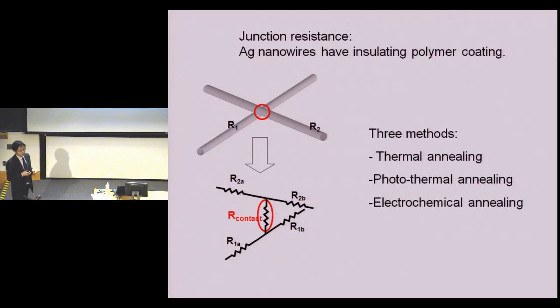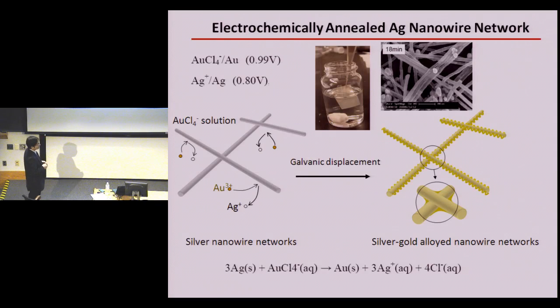So in our group, we found different ways to fuse the two junctions together to decrease the sheet resistance. I will show you the work I did using an electrochemical annealing method to decrease the junction resistance between the two wires. The principle is very simple, because silver has a lower reduction potential than gold. So the idea is, after we fabricate silver nanowire films on plastic substrate, we dip them into a gold chloride solution, and this kind of replacement reaction will happen.